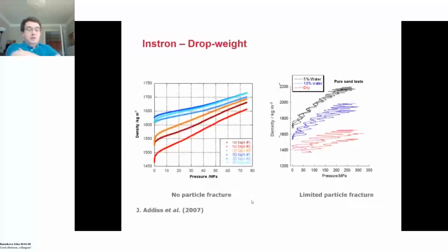Now, if you took just sand, so this is sand with an average particle size of around about 150 to 210 microns, and you pick it up from a beach, etc., and put it into a container and put it under a loading device and do it at very low rates, you will get responses as shown on the left-hand side here. There's a range of initial densities. That was something we did by just tapping the sand to compact it down under very low loading. So take the sand, just tap it on the laboratory bench, then measure the density. And we could get a range of starting densities.